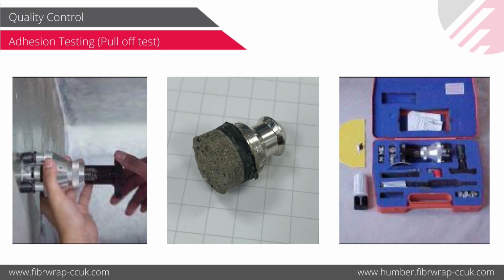So in the bond test, all we want to make sure is that FRP is bonded correctly onto the substrate, which shows that the preparation was correct, the saturation was correct, the installation was correct. The difference between this pull-off test, which we do for FRP strengthening, and the standard concrete pull-off test is that in the concrete test we look for a number in terms of pull-out strength, whether it's 2 MPa, 3 MPa, depending on grade of concrete. But in the FRP pull-off test, we are more interested in mode of failure.